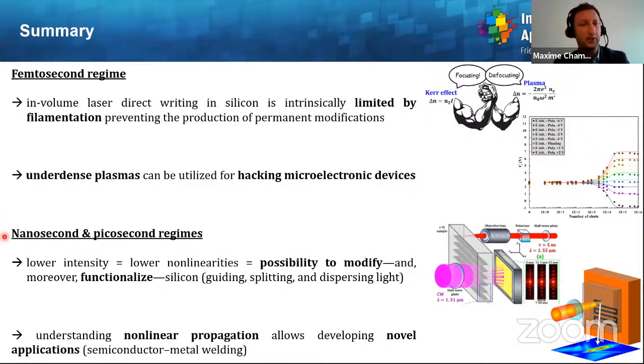And then in the nanosecond and picosecond regimes, the lower intensity leads to lower nonlinearities, and it is possible to modify and thus functionalize silicon with the inscription of optical elements inside the material for guiding, splitting, and dispersing light, for instance. And the best is yet to come, let's say. Also, the understanding of the nonlinear propagation inside silicon, especially the filamentation regime inside silicon, allows developing novel applications like semiconductor and metal welding.